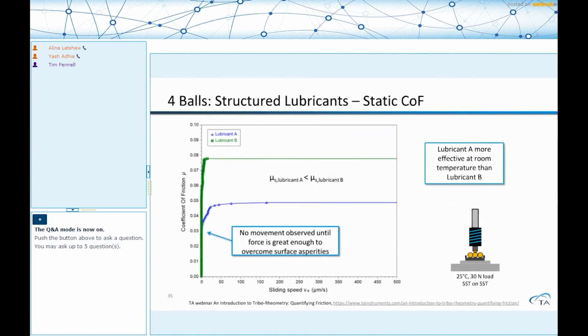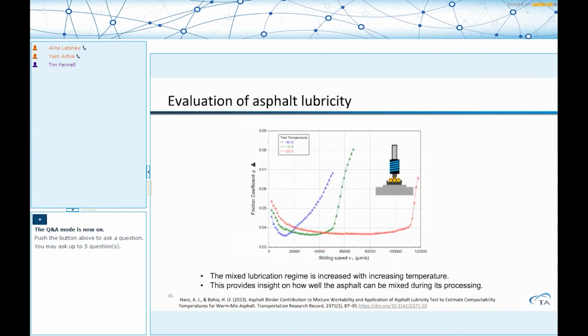Along the same token, what we'd mostly be talking about is dynamic friction, but there is an important concept in tribology, which is static coefficient of friction, which is basically, for those of you who are familiar with rheology, akin to yield stress in rheology terms, which means the two surfaces are at rest, and you're applying a force and they're not moving because the frictional force is resisting it. And so the coefficient of friction that you measure under these set of conditions is called the static coefficient of friction. And again, here you can see, initially at low sliding, like when the sliding speed is 0, because you're just increasing the torque acting on the system, and as the torque keeps on increasing, eventually the material starts moving, and that's when you see a big shift in the sliding speed.